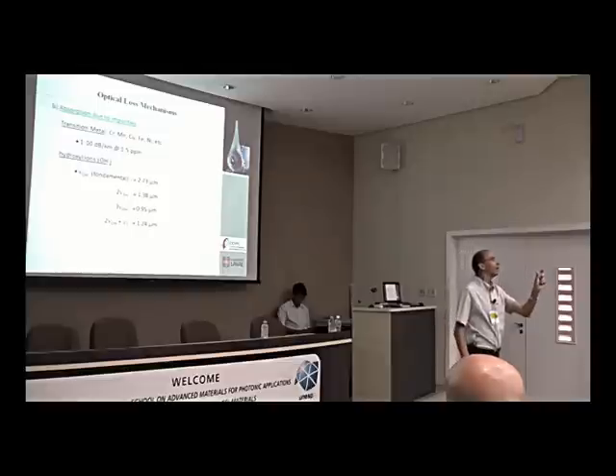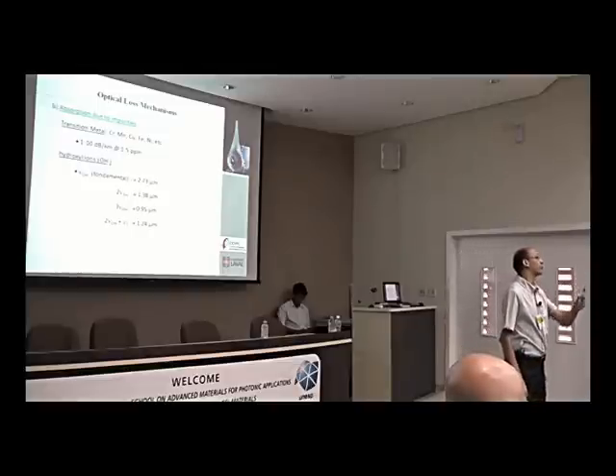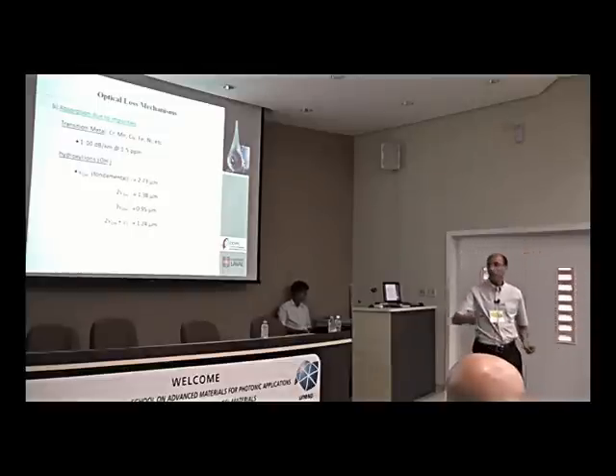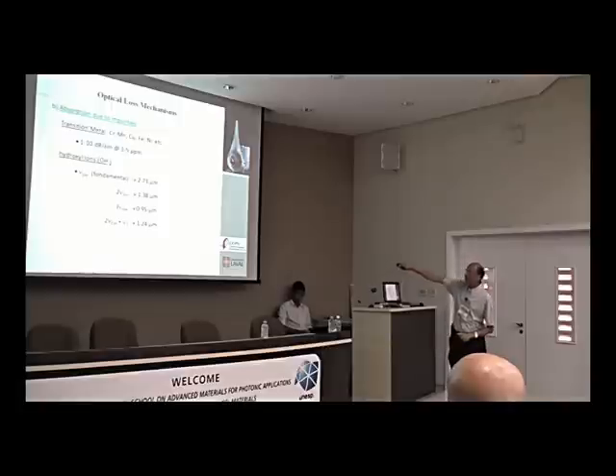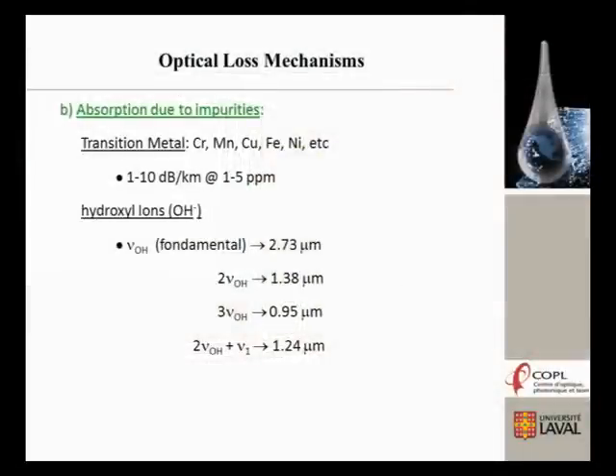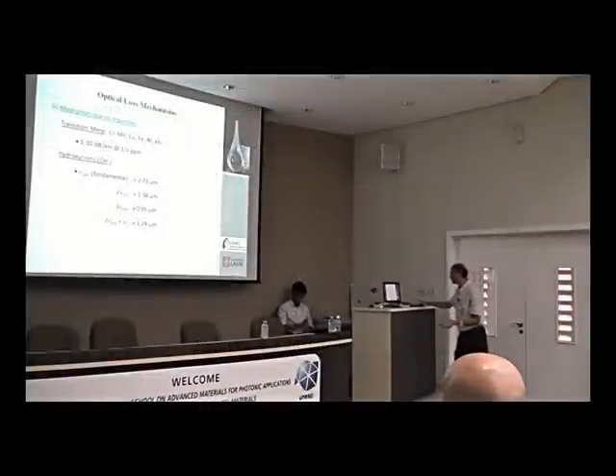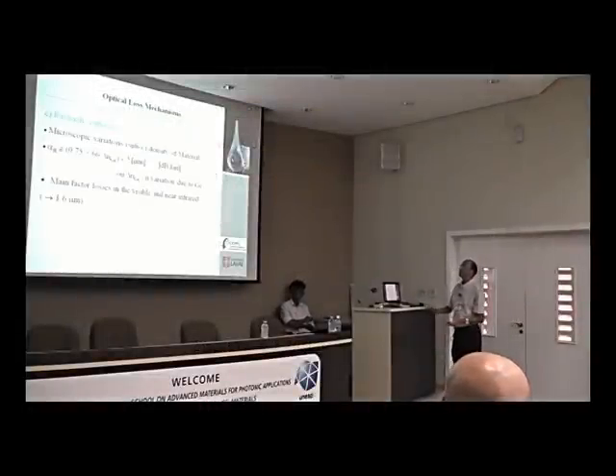This peak, I didn't say in the beginning, is the OH group. The OH group in silica, the fundamental of that is at 2.9 micron, or 1.4 micron, 0.95 and 1.24. Did you see several absorptions of the OH group that affect the optical quality of the fiber? We solved all these problems.